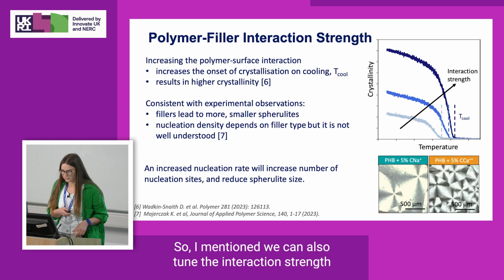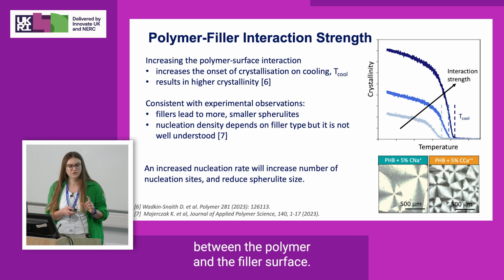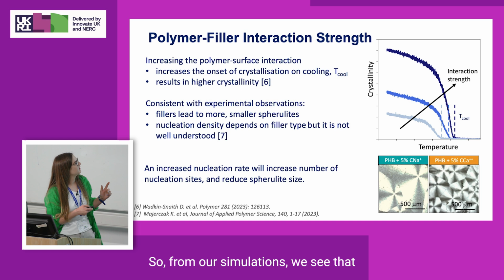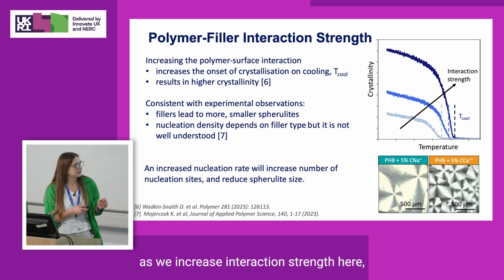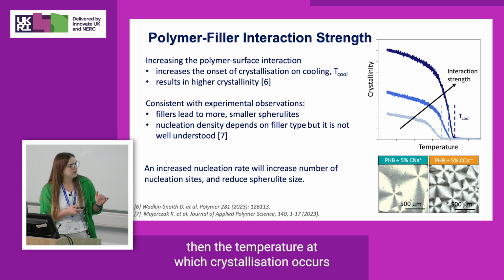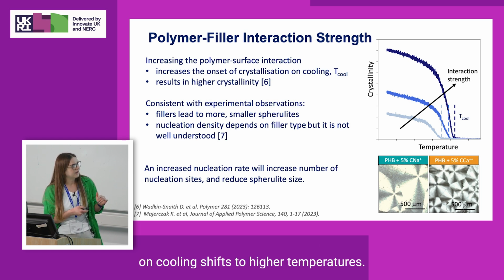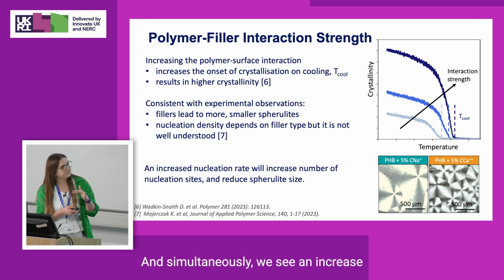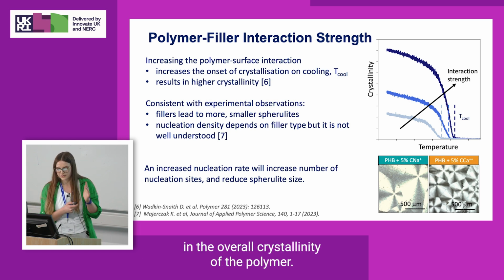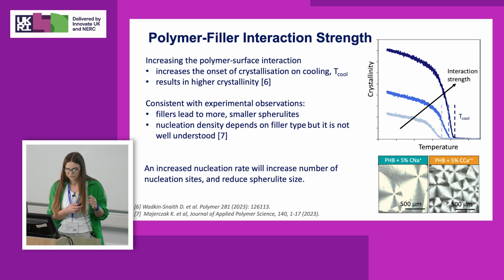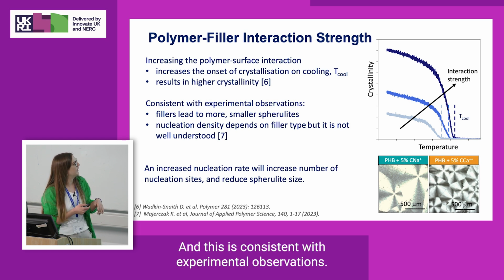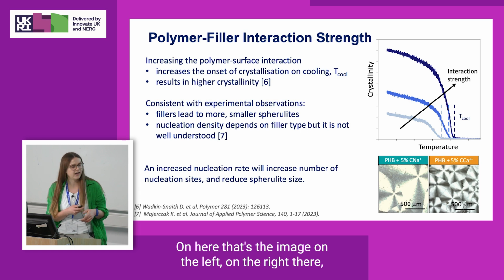So I mentioned we can also tune the interaction strength between the polymer and the filler surface. From our simulations, we see that as we increase the interaction strength here, going from light blue to dark blue, the temperature at which crystallization occurs on cooling shifts to higher temperatures. And simultaneously, we see an increase in the overall crystallinity of the polymer. And this is consistent with experimental observations.